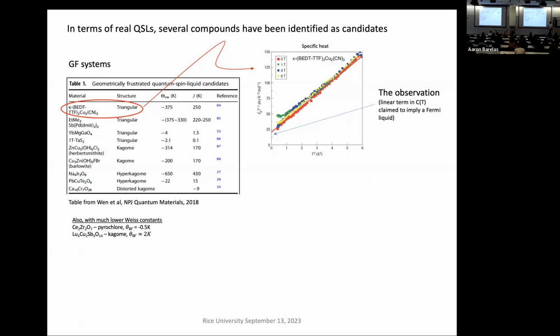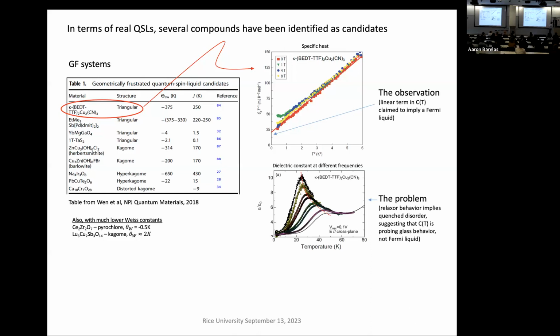It was claimed to be a Sommerfeld coefficient and comes from a Fermi liquid. How that can happen in a spin system, you'll need to read Savary and Balents' review to understand. But the problem is that this is actually a relaxor. This shows the dielectric constant as a function of temperature at different frequencies. And the problem is that relaxor behavior implies quenched disorder.